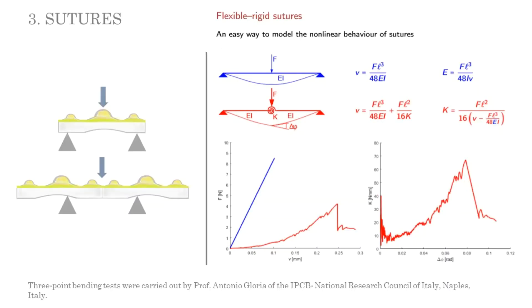We analyzed the mechanical behavior of plates and sutures — the plate-plate system — by means of three-point bending tests. These tests were used to calibrate the parameters that characterize the sutural behavior. Results showed a peculiar behavior of the plate-plate systems: while single plates behave linearly until rupture, plate-plate systems allow a limited relative rotation between plates. In particular, sutures exhibit a very flexible bending behavior when rotations are small. Subsequently, when rotations become larger, the stiffness of these joint systems hardens and limits the final mechanism.